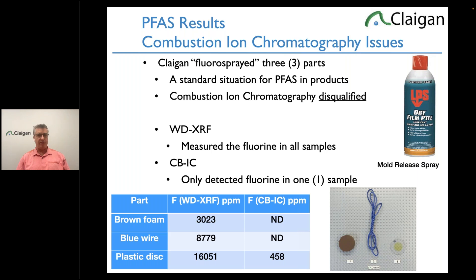Surface coatings are a big deal for both the EU and the US — almost everything they're restricting in the US is surface-related. We just can't use combustion ion chromatography for that. We do use it for lithium batteries, which use PVDF and PTFE as a binder in the cathode. We can't safely dismantle lithium batteries, so we incinerate them and measure the fluorine. Same with supercapacitors. Otherwise, it's really all WDXRF. If you're not doing WDXRF, you're going to miss a lot.